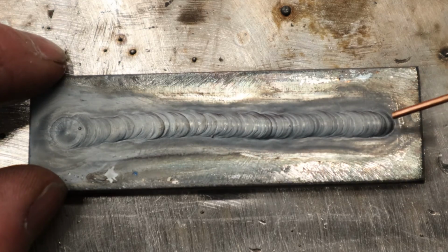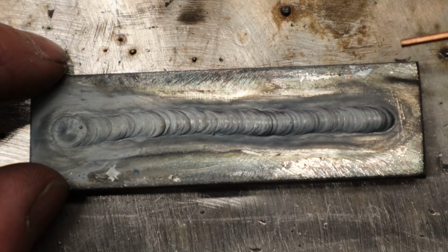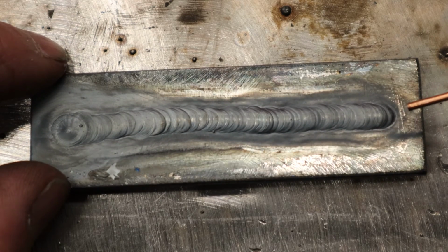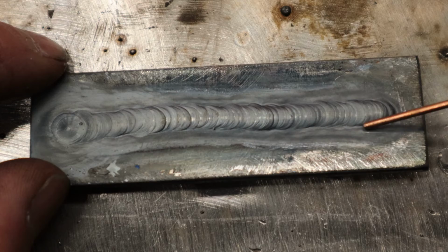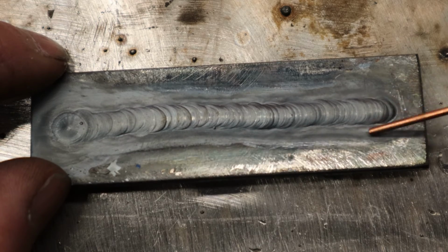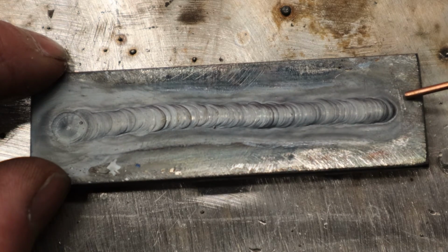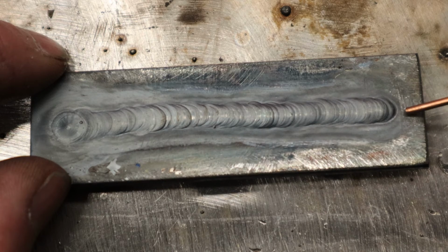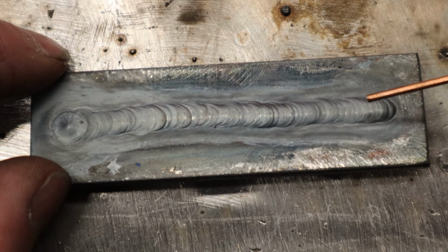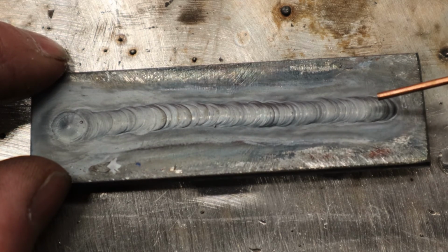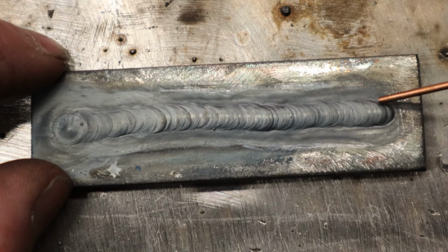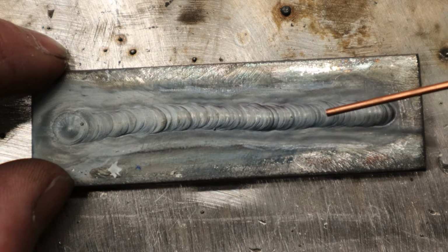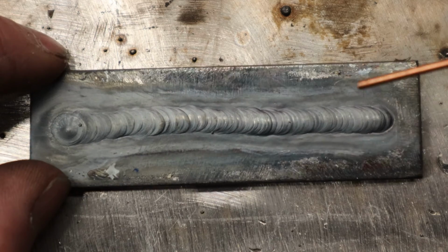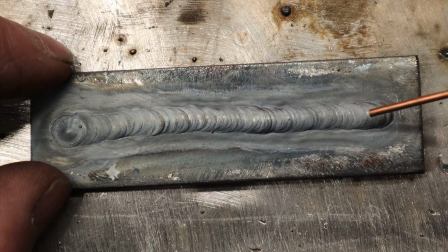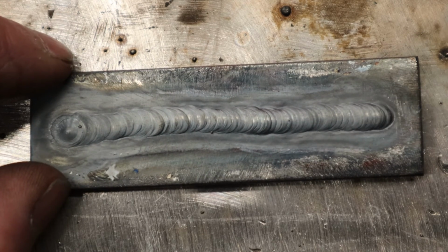All right, let's take a look at this weld. So I started here and went in this direction, and the first thing I look for is, is it too hot or too cold? Well, there's a decent kind of lump to this weld bead, so that's good. It's not concave or flush with the surface, meaning it's too hot, and it's not sitting up like a bird poop or a worm on top, meaning it's too cold. Now, the width of this weld bead is a decent size, and it stays consistent throughout, so that means the heat didn't change and the amount of filler rod was pretty consistent.